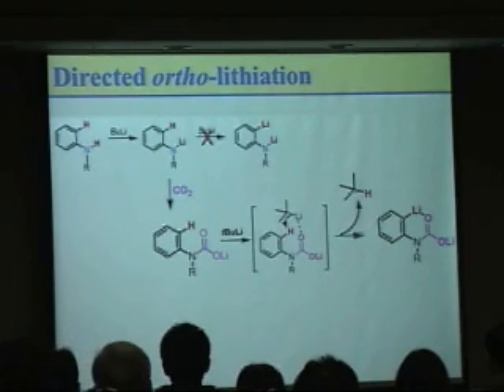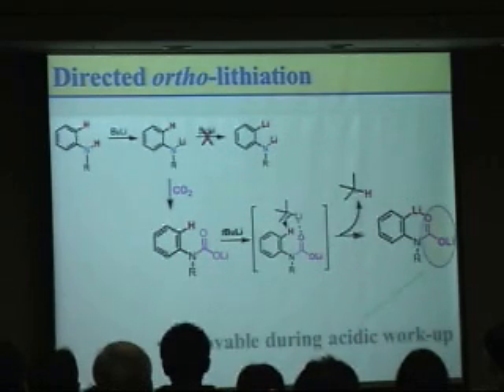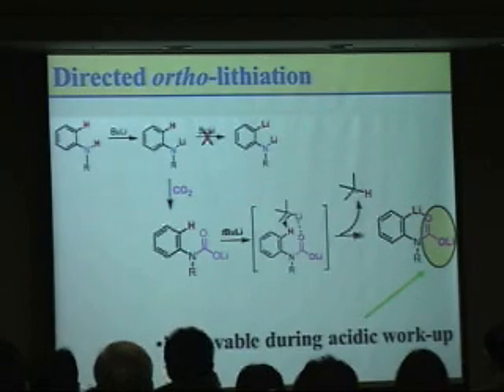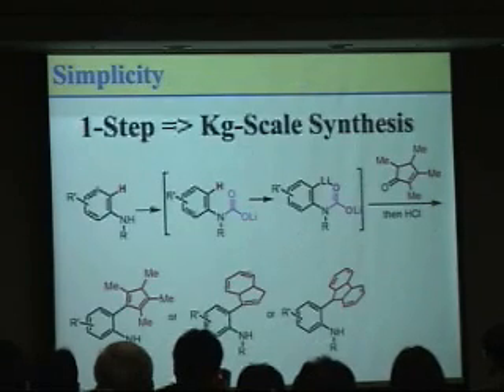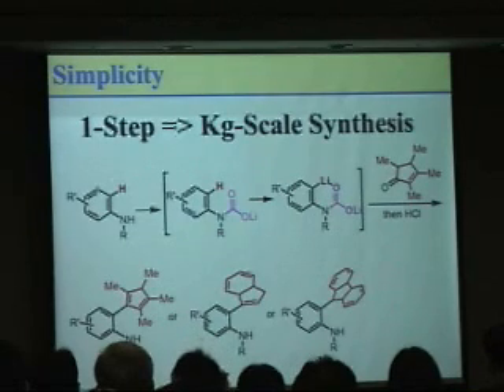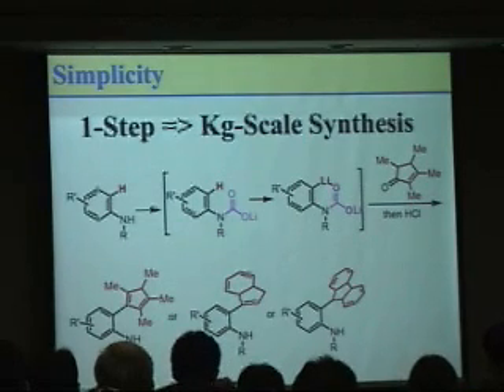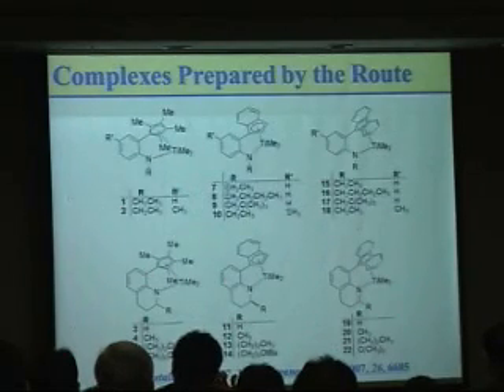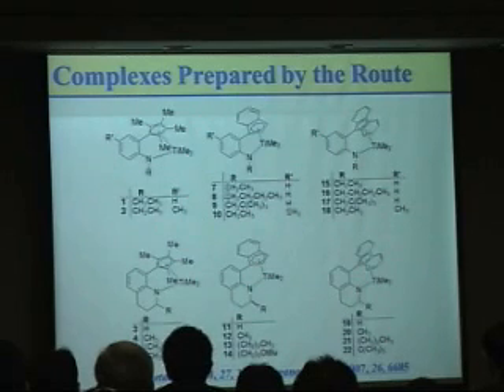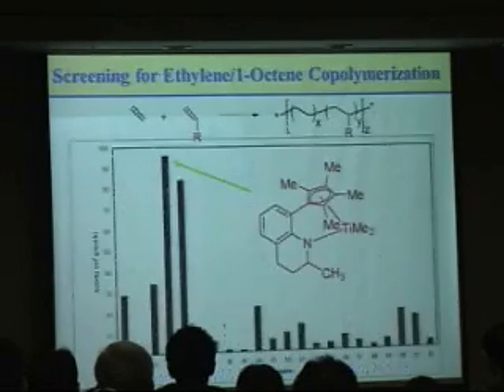This is a very fundamental chemistry developed by myself to achieve the target complex, and this lithium carbamate group is easily removed to convert to the secondary amine group by just an acid workup procedure. So using this fundamental chemistry developed by myself, I was able to prepare the targeted ligand on a kilogram scale in just one step. And then I was able to prepare 22 new complexes based on the synthetic scheme. Among the 22 complexes, this catalyst shows the best catalytic performance.